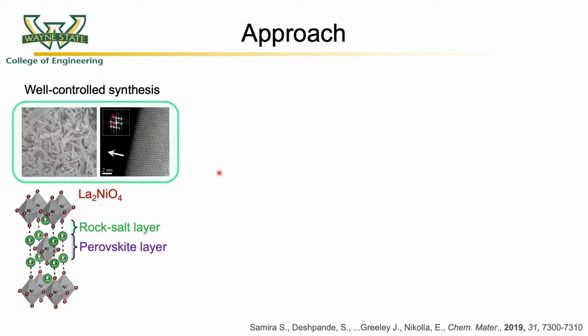Our approach involves atomically controlled synthesis of first series Ruddlesden-Popper oxides of the general form La2NiO4. These oxides have been shown to exhibit excellent electrocatalytic activity, and are made up of non-precious metal-based systems like lanthanum and nickel. These oxides exhibit a tetragonal symmetry where the perovskite layer is separated by a rock salt layer, and the perovskite and rock salt layer continue on in the z direction.